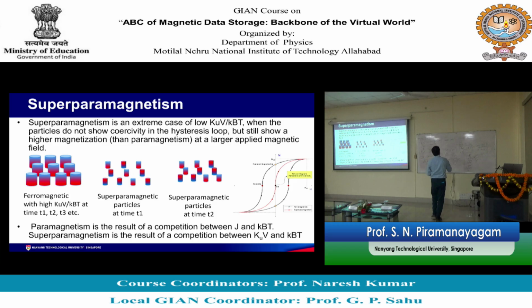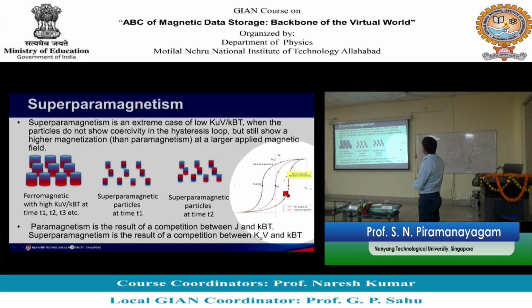So, the particle will have high Ms. Ms is not affected because the material is still ferromagnetic. It is not a paramagnetic material. The neighboring spins are parallel. So, if you apply a high magnetic field, all the spins will point in the direction of your applied field. So, they will exhibit as high Ms as any other material. For example, I use the same material, let us say cobalt. This is cobalt with larger diameter grains, cobalt with smaller diameter grains, cobalt with even much smaller grains. So, this sample and this sample will show the same Ms, but this particular sample will show coercivity in the hysteresis loop, this one will not show.